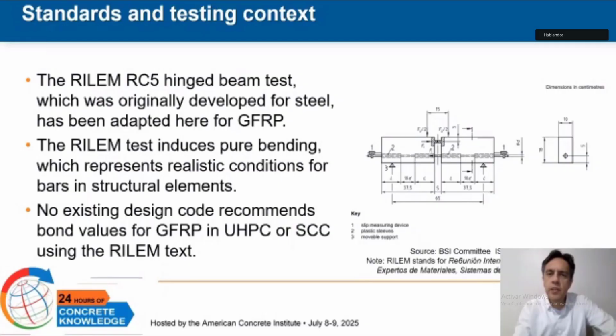To address these limitations, our study adopted the RILEM RC5 hinged beam test method, which was originally developed for steel rebars but was adapted for GFRP in this study. This configuration induces a pure bending moment, producing a bond-slip response under more realistic stress conditions.